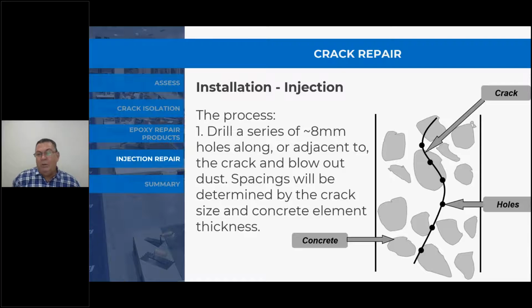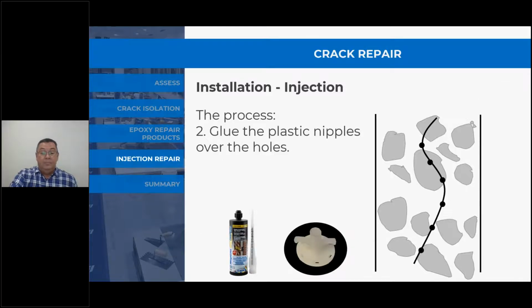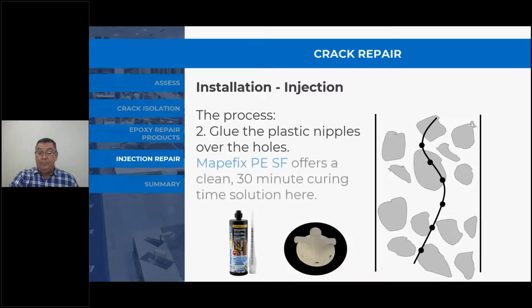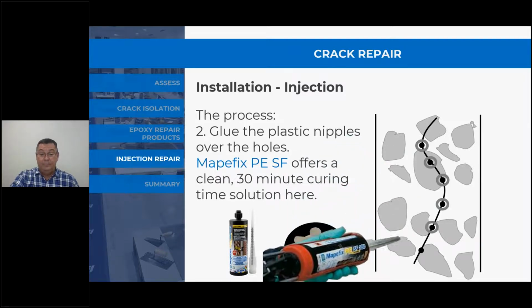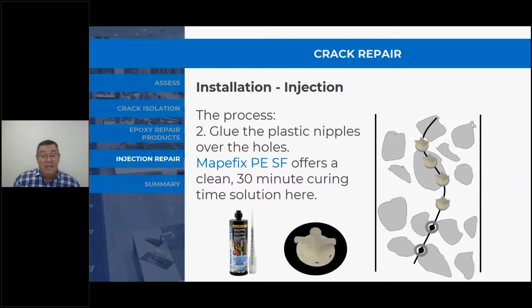So generally, as a rule, if the concrete was 150 mil thick, then you would start at something like 150 mil spacings, and they can become wider depending on the size. If the cracks are wider, then they can be further spaced apart. So glue the plastic nipples over the holes, using the Mapefix PE SF, which is a fast curing polyester resin adhesive. It takes about 30 minutes to fully cure.